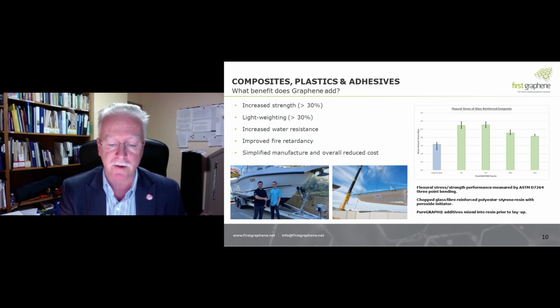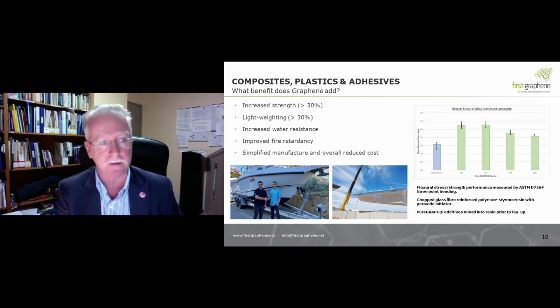The hydrophobic feature of graphene prevents the ingress of groundwater that can lead to blistering on the surface of the pool walls. Same benefit applies to fiberglass boats. You wouldn't need to dry dock the boats for a month each year, as they wouldn't absorb the moisture in the first place. The fiberglass composite market is worth about $60 billion US per annum. Many fiberglass products could benefit from the addition of graphene. Carbon fibres can also be made stronger with graphene, and according to our customers, they can reduce manufacturing costs by 10%.